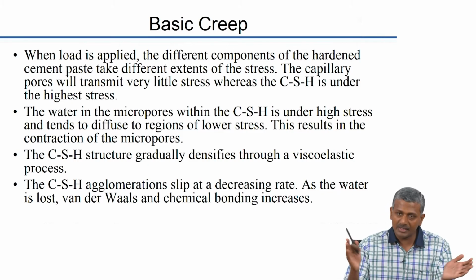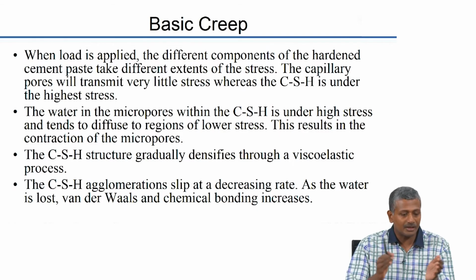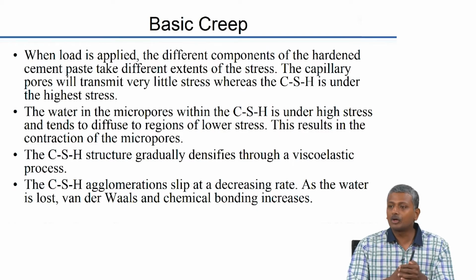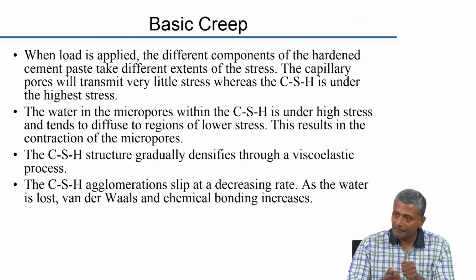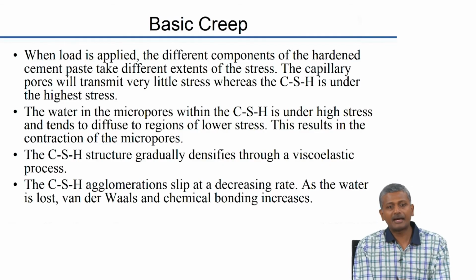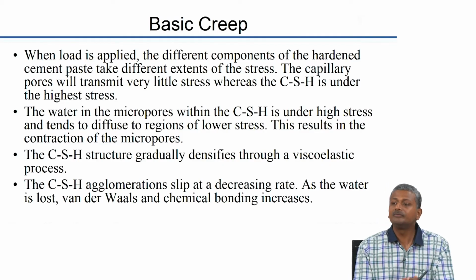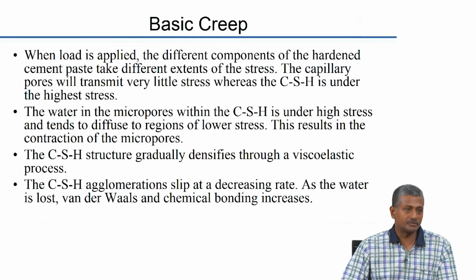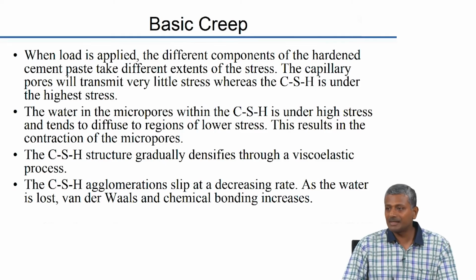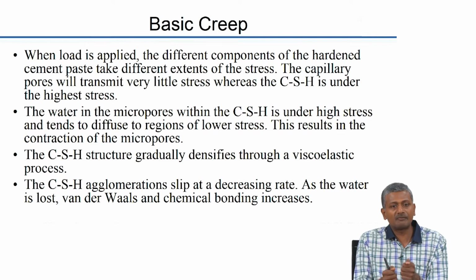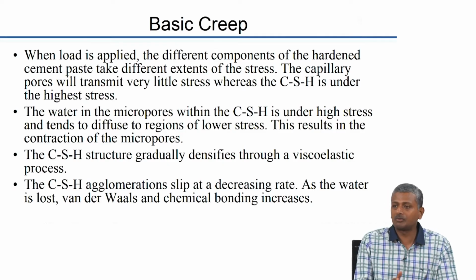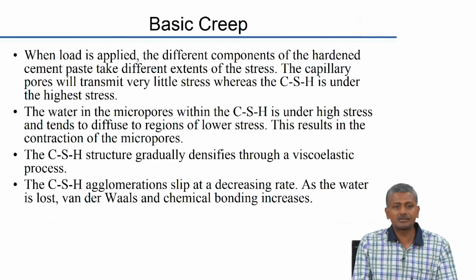So, CSH gradually densifies because of the viscoelastic rearrangement, and again the agglomerations of CSH will start slipping. That means there will be some sliding happening between the layers, and that will lead to a lot more volumetric deformations. So, when water gets lost, your chemical bonding will start increasing, the CSH itself will increase very highly in strength, but your overall concrete deformation will be high, which will lead to failure strain being approached much